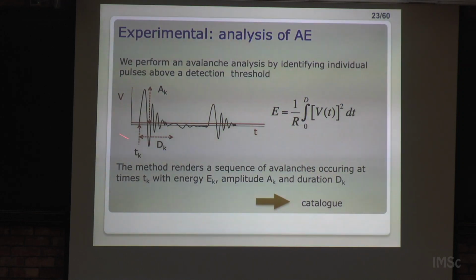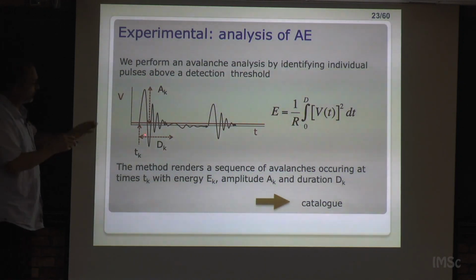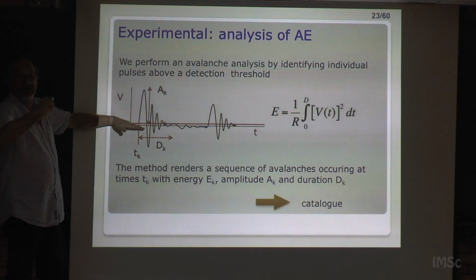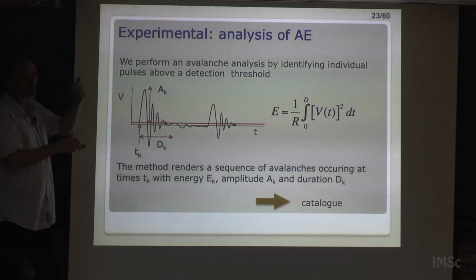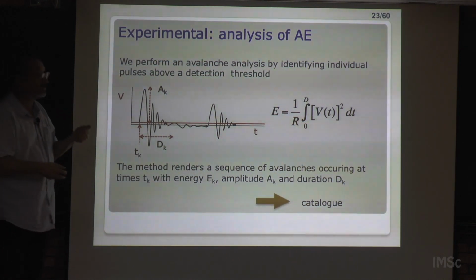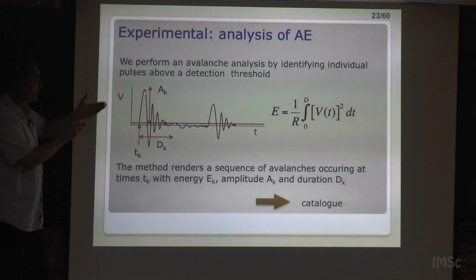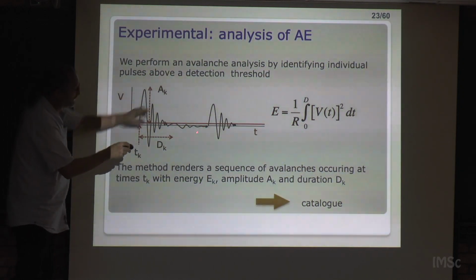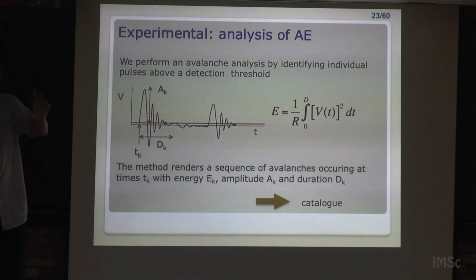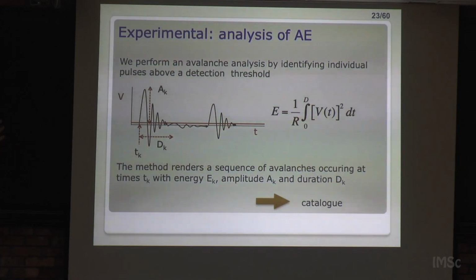And this is a typical signal that we get. It's a schematic, but the idea here is to define the parameters that we measure. So this black line is the voltage that we register, and what the machine is doing is taking data at 40 megahertz, very fast, and just trying to measure this curve. And then automatically the electronics is measuring. First of all, we need a threshold to define when the signal starts, and then we need also a way to define when the signal ends. And this is done by defining what is called a hit definition time. When the signal is below threshold for more than a certain time, it means that the signal stopped. And this is something that we can control, but there's no way to separate events if we don't put that.